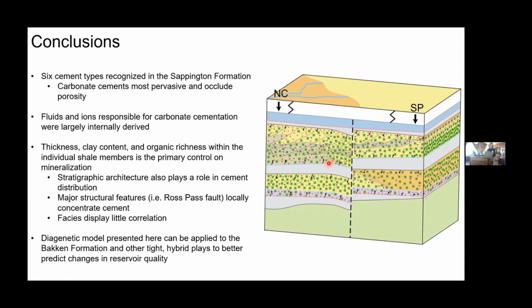So there are 6 cement types recognized in the Sappington, with the carbonate cements being the most pervasive and occluding porosity. The fluids and ions responsible for carbonate cementation were largely internally derived. The thickness, clay content, and organic richness within the individual shale members is the primary control of mineralization. But there's also some stratigraphic architecture, in that upper siltstone in particular, that plays a role in cement distribution. The major structural features, aka the Ross Pass fault, locally concentrated cement.